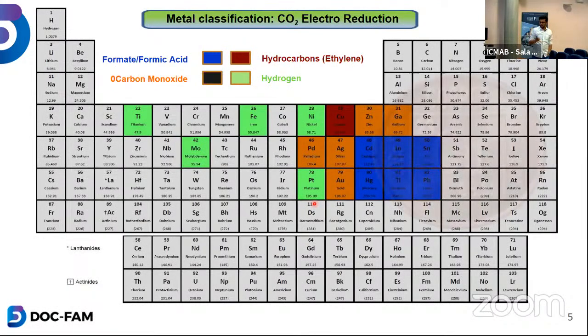When we go to the periodic table and look at the different elements, all the transition elements are very good for the hydrogen evolution reaction. Then we have cadmium and indium, metals which are good for formate or formic acid products. Then palladium, silver, or aurum, like gold, the noble metals, are good for carbon monoxide. And then we have only copper, which is actually good for hydrocarbons.